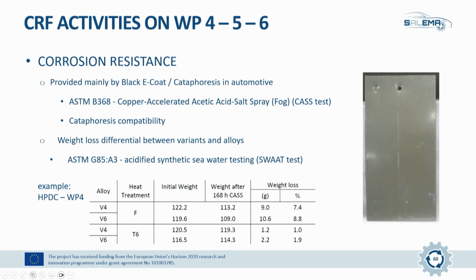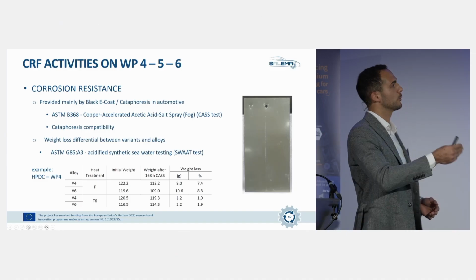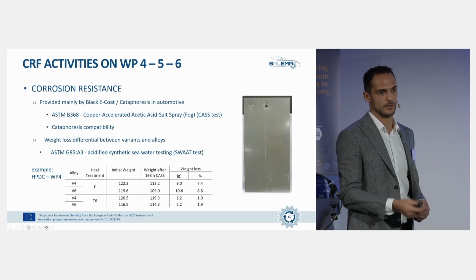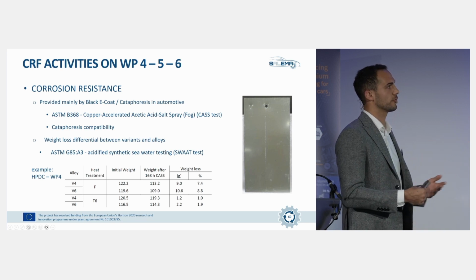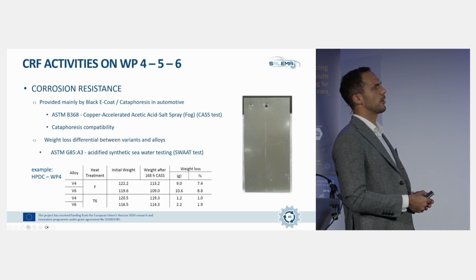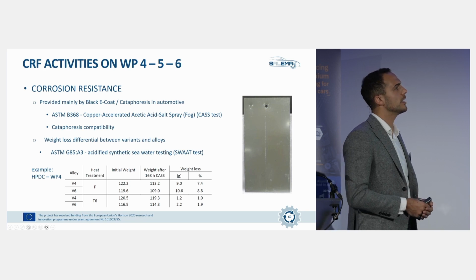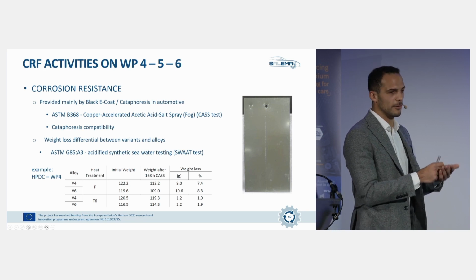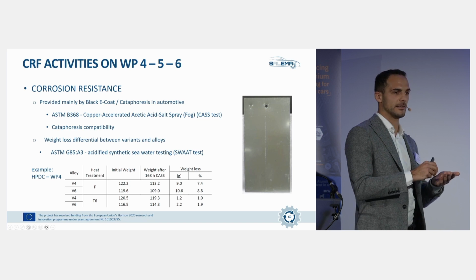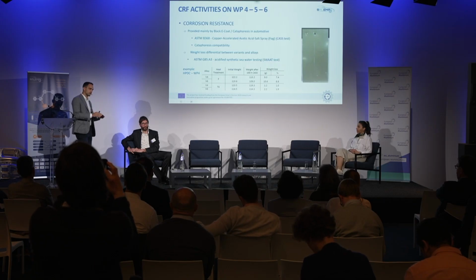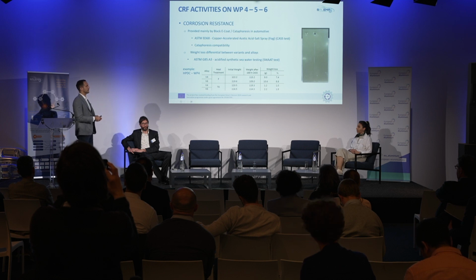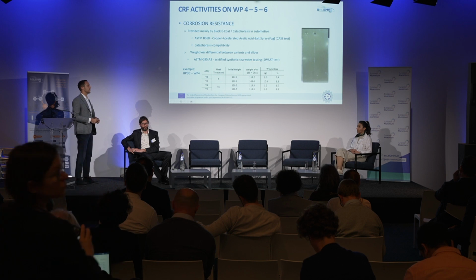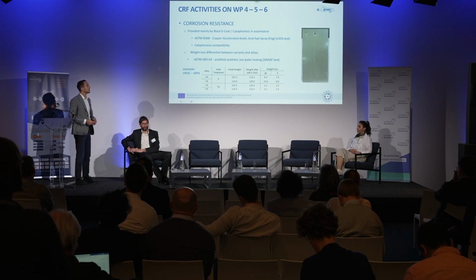Then manually we did a scratch. Then we did a CASS test, a corrosion chamber for, if I remember well, 168 hours. Then manually a scratch, like with duct tape, and then you evaluate how much of the corrosion went below the cataphoresis. For all 3 work packages, so for all 3 kinds of alloys, the results were okay.